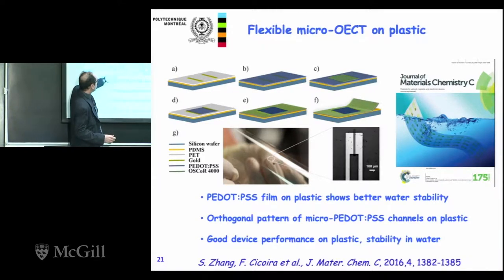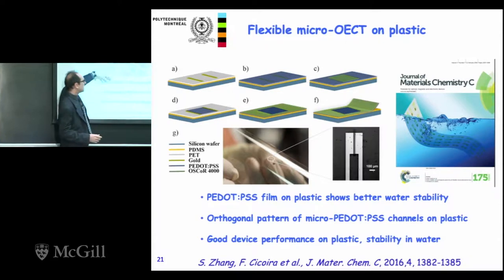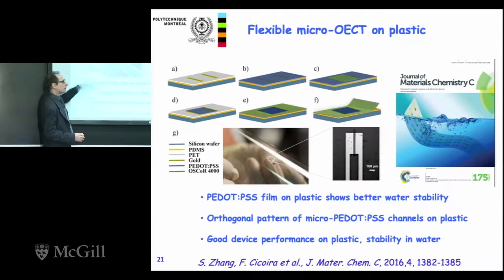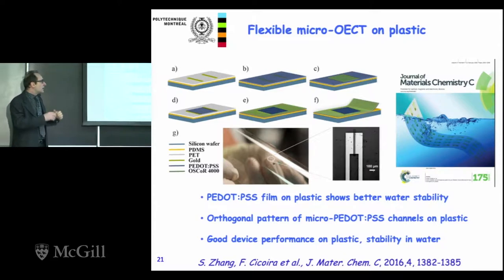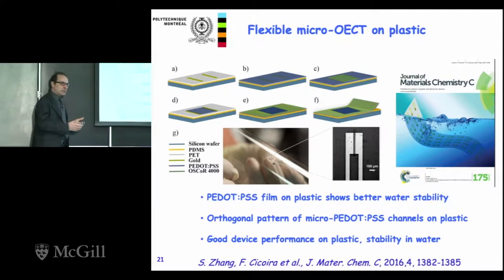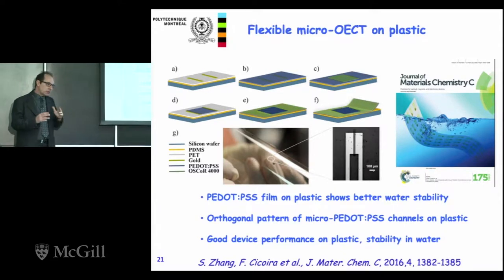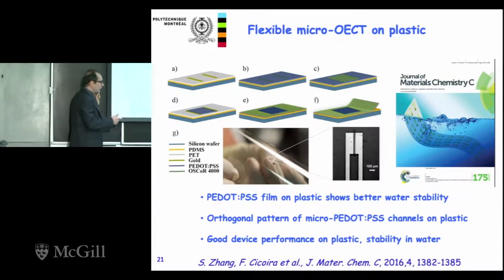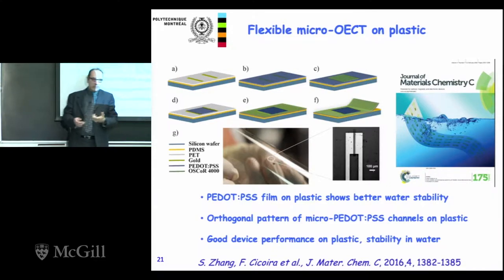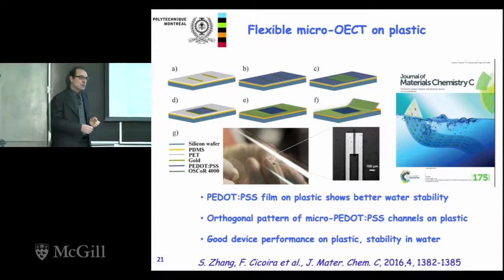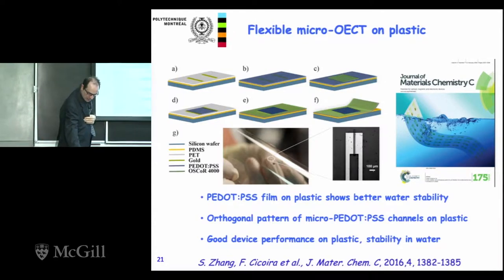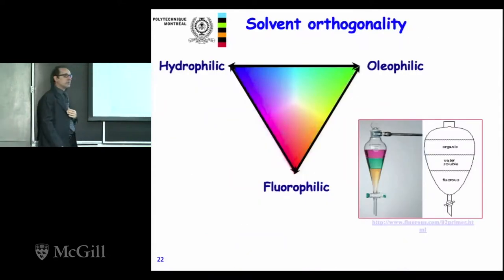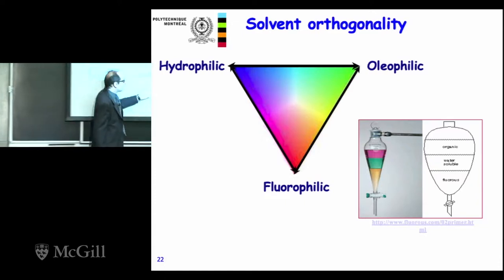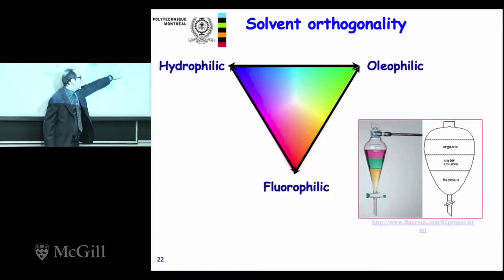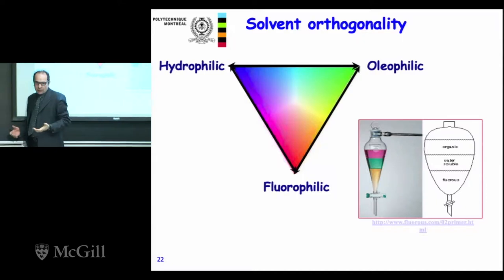So actually what we can do, we can cut our PET in form of wafer that we can process as if it was a silicon wafer. The only thing we do, we change completely the chemistry of the lithography. So instead of using the traditional photoresist developer and etcher, we use a completely different product line, which is based on fluorine chemistry. And the reason why it works is that you know that fluorinated materials, they are completely orthogonal to aqueous and organic systems. They are not miscible with both of them.